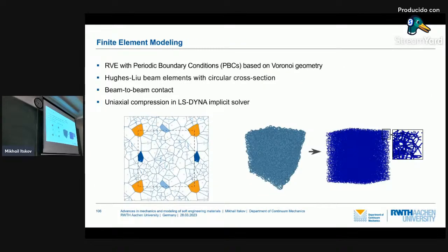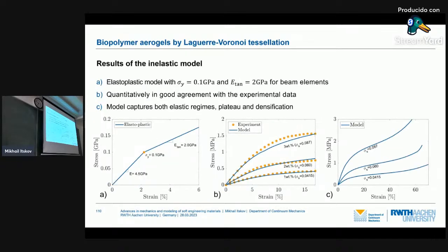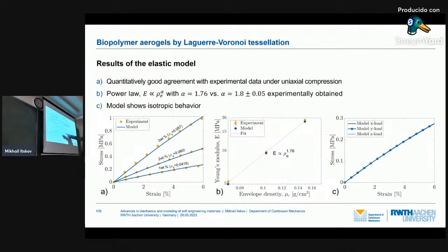Right, and this shows then the finite element simulations, based on this RVE with periodic boundary conditions. You see here such an RVE for 2D, but it's also done for 3D, and you see here how it happens. Then we apply beam elements for these connections. Beam contact, and also friction between these beams is taken into account, and everything is then calculated using an implicit solver. The results you can see here. For example, for the elastic model, you see good agreement for stress-strain curves for different amounts of particles here, right? And also good agreement for the so-called Gibson-Ashby law.